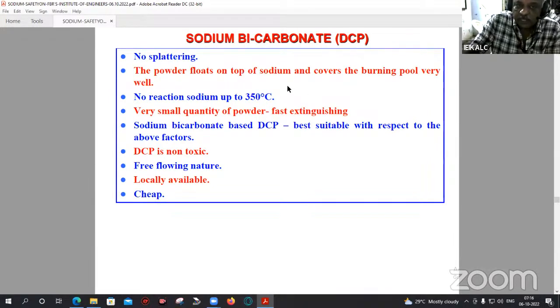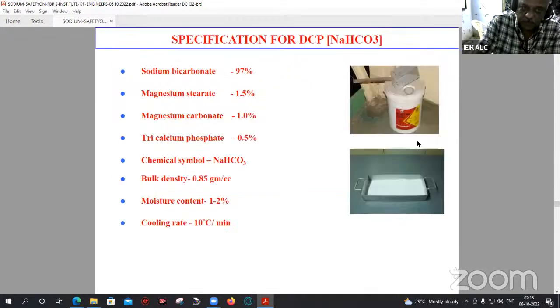And there was no reaction between sodium bicarbonate and sodium up to 350 degrees centigrade. And the quantity needed was also less. And this is non-toxic, free-flowing. When you are making the powder come out of an extinguisher, the free-flowing nature is very, very important, and it's very, very cheap, around 60 rupees per kg. And this is the standard specification for a dry chemical powder used in our sodium systems, like sodium bicarbonate, magnesium stearate, magnesium carbonate, tricalcium phosphate, etc. And see the moisture content. This is very, very important, and the cooling rate also. Suppose there is a sodium leak, we tested on sodium leaks where the powder was used, and the cooling rate was also observed to be quite good.